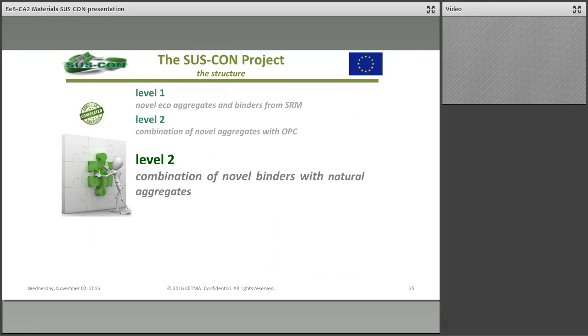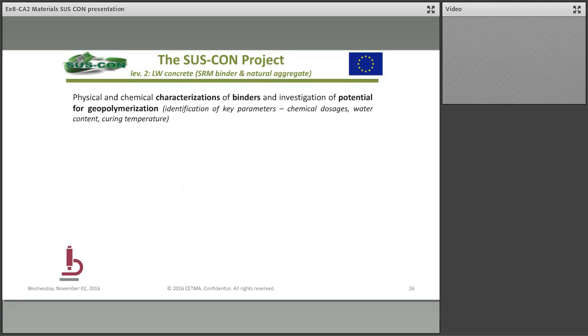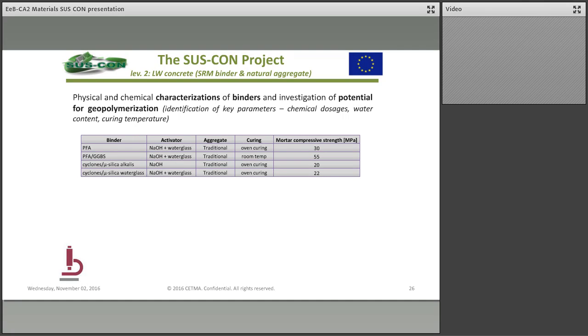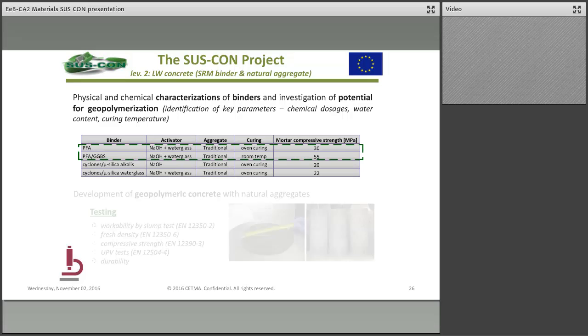Okay, the next step was to check the suitability of the novel binders from secondary raw materials to be used with natural aggregates. To this aim, physical, mechanical and chemical characterization of binders were performed, aiming to investigate the potential for geopolymerization. And a lot of tests were made in order to identify the process parameters for geopolymerization, and these were the main results obtained for PFA and GGBS based binders.